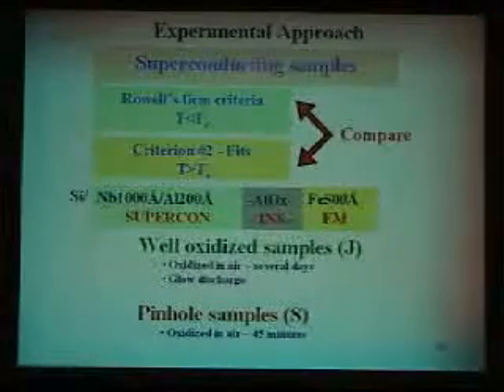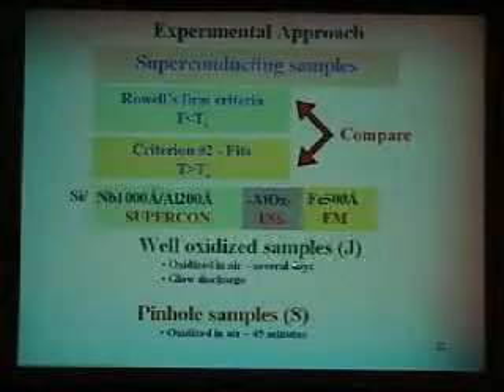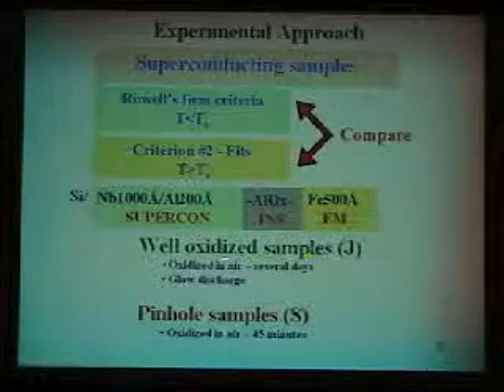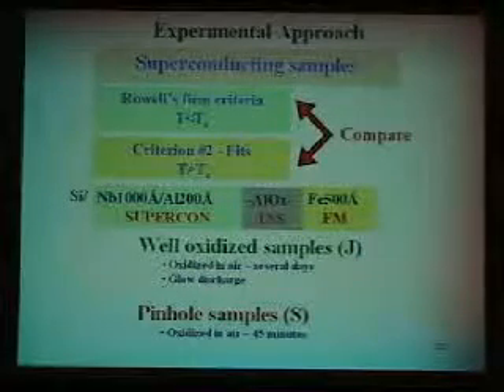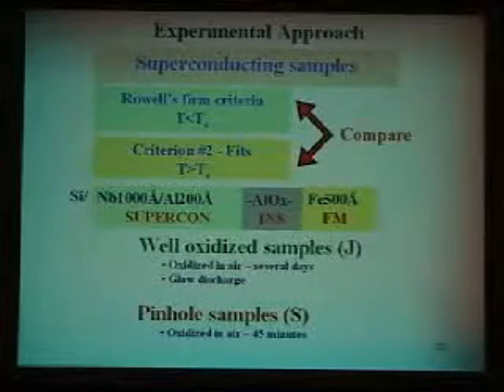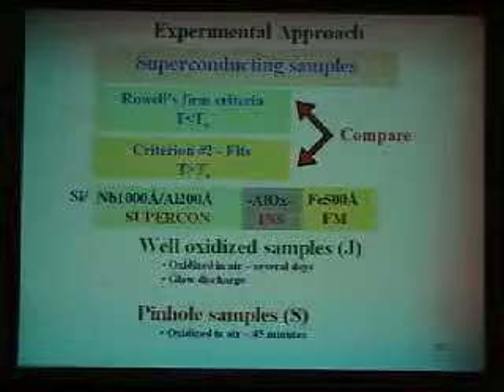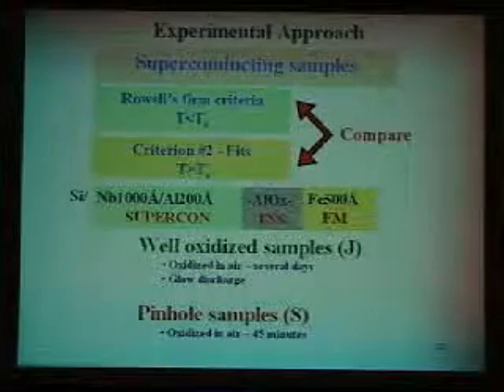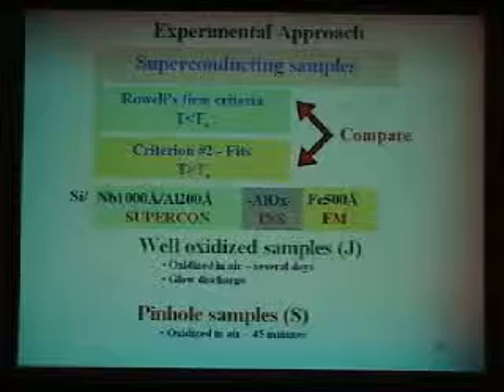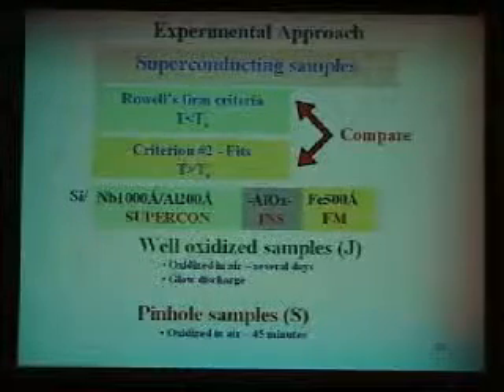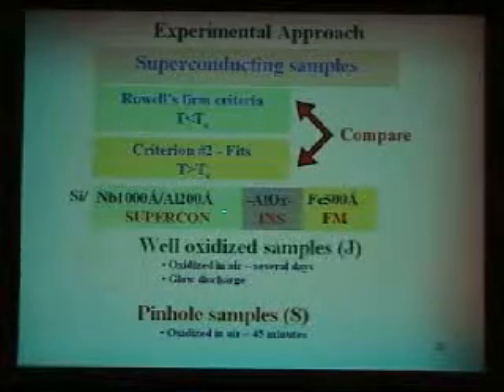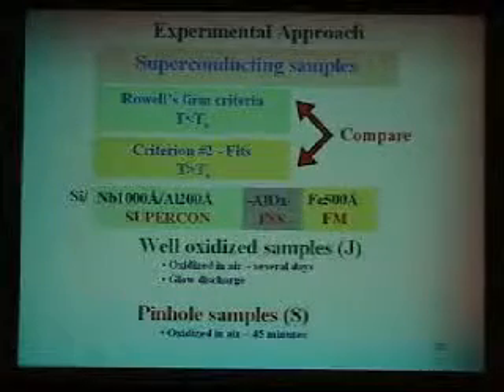What they call a well-oxidized junction, which is this one, I'll always indicate by green, and it's going to have a J in front of it. It is oxidized in the air for several days, and then glow discharged. Another one, which I call a pinhole sample, is always indicated in red, and is oxidized in the air for 45 minutes only. We make lots of these. Mind you, it's not just one sample, it's hundreds of samples.